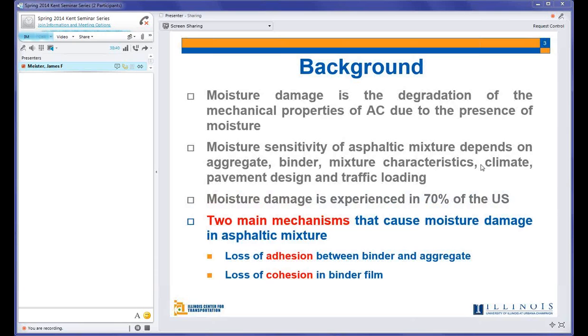When moisture exists in asphalt concrete, it deteriorates the asphalt through two main mechanisms: the loss of adhesion, where the bond between the aggregate and the asphalt binder weakens, and loss of cohesion, where the bond within the binder itself starts to weaken. Now, the problem statement, why did we do this study?